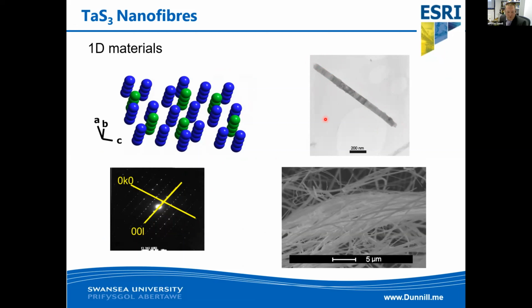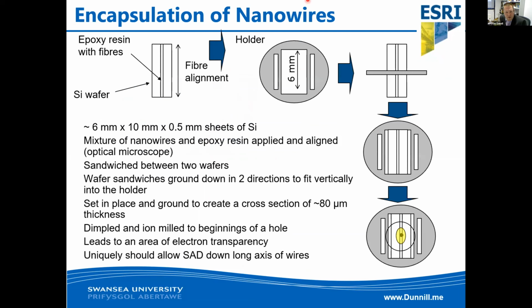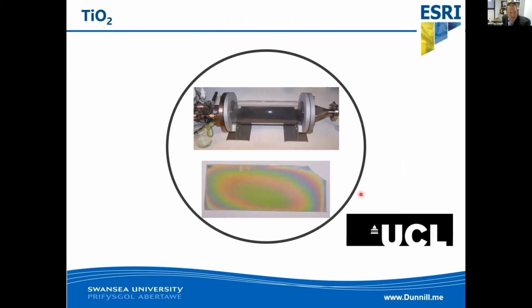Being able to take electron diffraction patterns down the actual length of a nanofiber was quite an interesting challenge. So very briefly, we're able to encapsulate these nanowires into epoxy resins. You can align the fibers down with a silicon wafer. You can put them into a little holder for the TEM. You chop the top off and the bottom off, and then you grind away until you have a vertical alignment of nanofibers in this middle section here. That's so thin that it's electron transparent. And that way you can get electron diffraction patterns down the actual lengths of these nanofibers. So that was quite interesting.